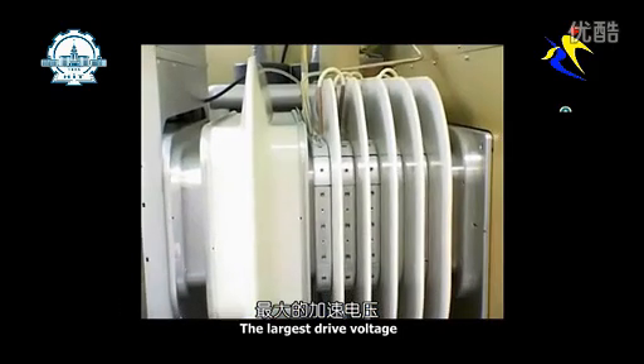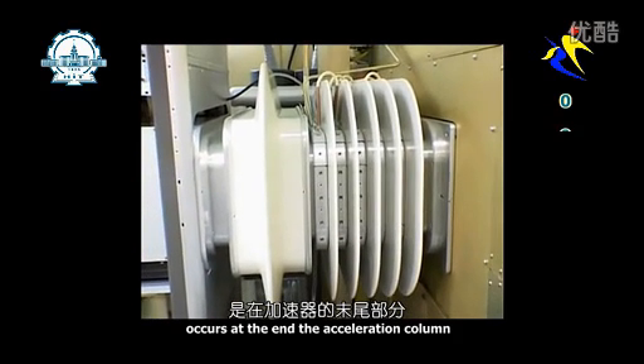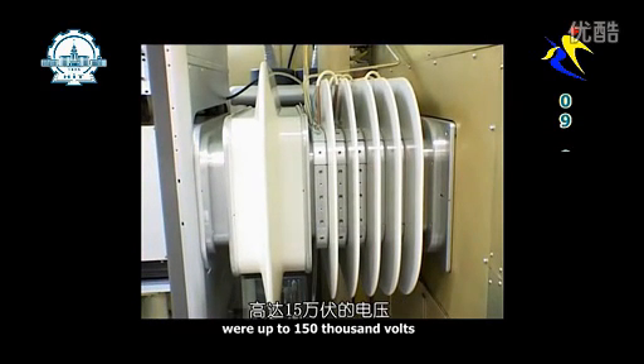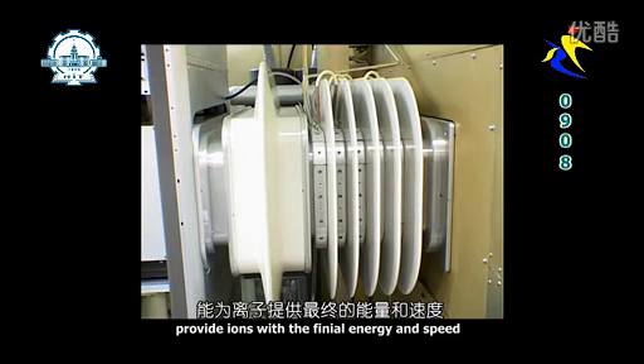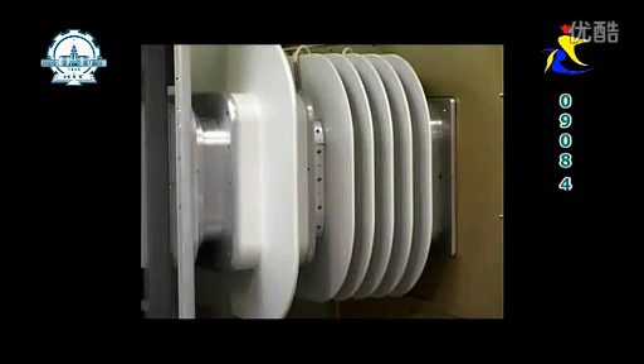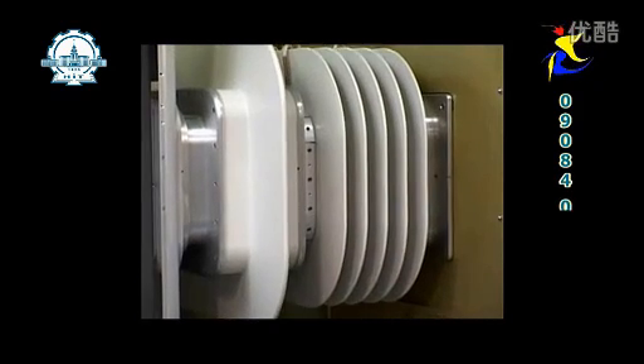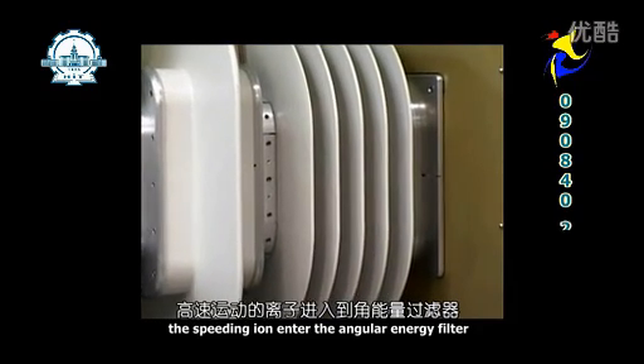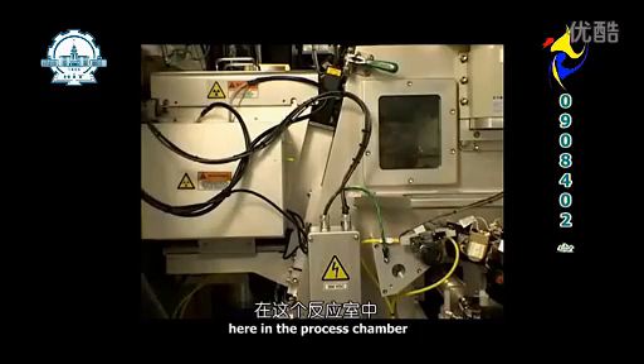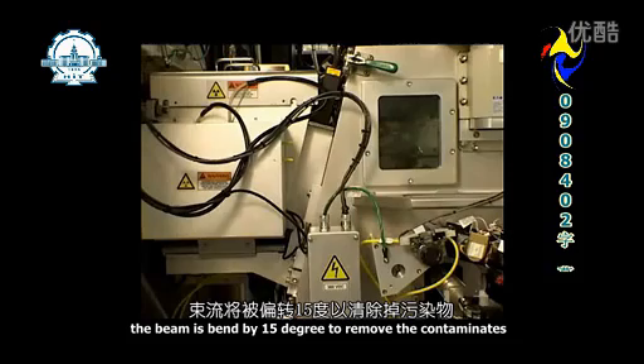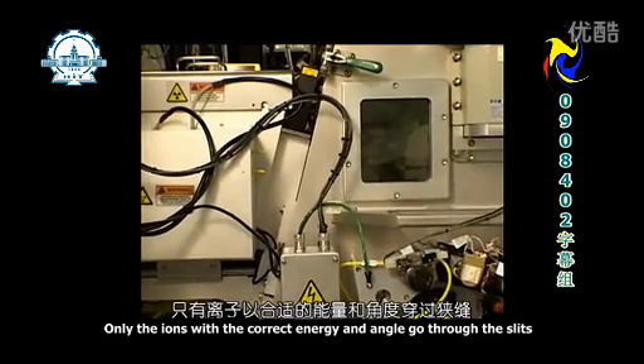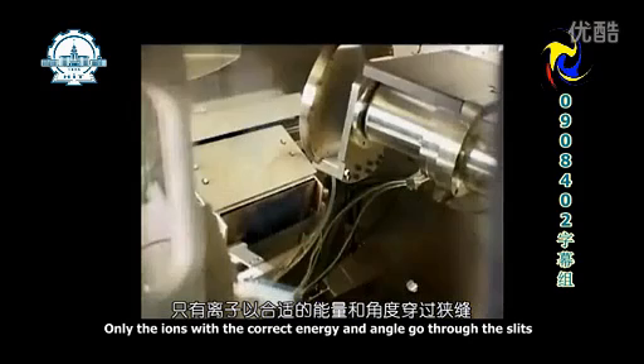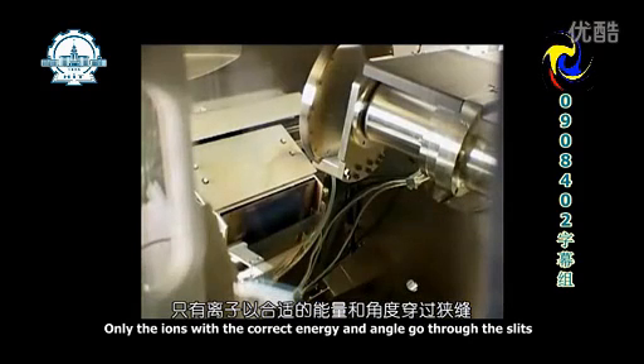The largest drop in voltage occurs at the end of the acceleration column, where up to 150,000 volts provide the ions with their final energy and speed. In the next station, the speeding ions enter the angular energy filter. Here, in the process chamber, the beam is bent by 15 degrees to remove contaminants. Only the ions with the correct energies and angle go through the slits.